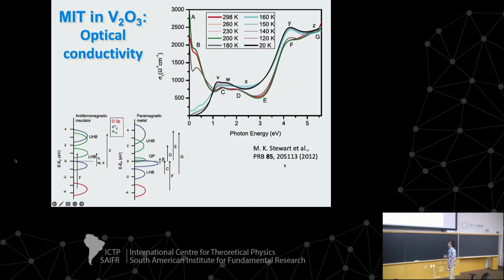Okay, we saw optical spectroscopy this morning, so I wanted to show you also beautiful optical spectroscopy data on this material. So indeed, in the paramagnetic metallic state, there is a Drude-like peak at low frequencies, and then the optical conductivity decreases, and then you have high energy interband transitions. All of them are labeled here, and some of them are interpreted as transitions from the lower Hubbard band to the upper Hubbard band or to the conduction band.